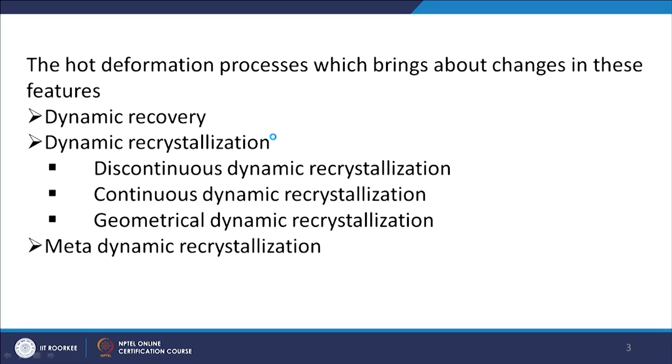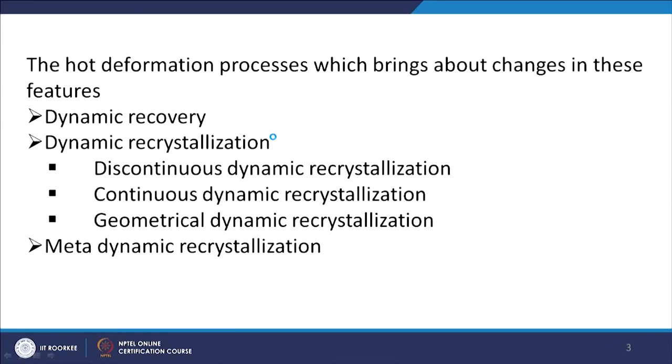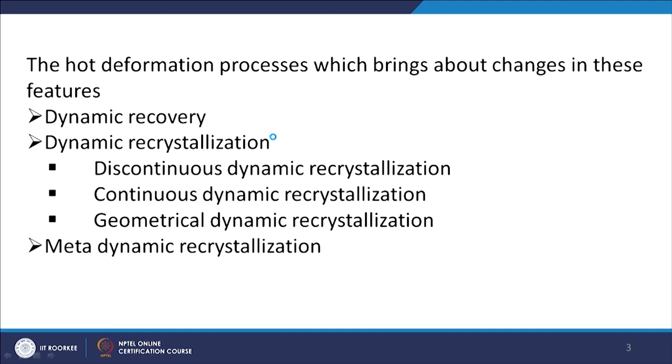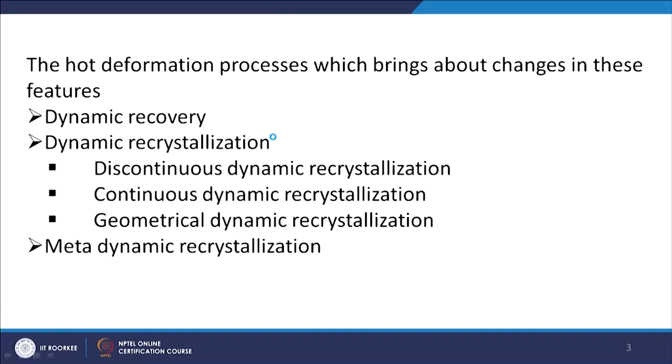In dynamic recrystallization, two or three distinct processes have been identified by researchers. These are discontinuous dynamic recrystallization — also called classical dynamic recrystallization — where you have nucleation and growth. Then there is continuous dynamic recrystallization; recently people feel it is the most common and discontinuous takes place only in a few cases. And then geometrical dynamic recrystallization and metadynamic recrystallization. We will see these recrystallization processes in detail.